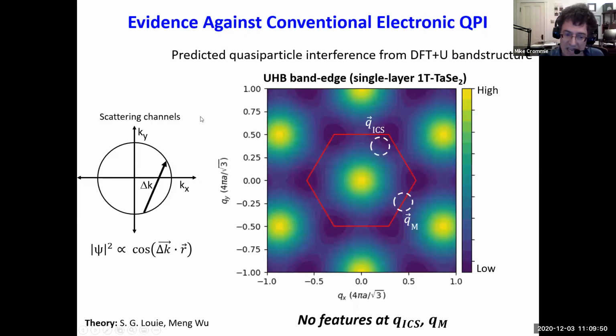And so our theory collaborators calculated the QPI pattern that you would expect for 1T TaSe2 using the DFT plus U band structure. And so here you can see that if you go, for example, near the Hubbard band edge, then you really don't have any features that would lead to periodicities at these QICs and QM. There's really no features there. There's no features in the electronic structure, at least no obvious features that would lead to that QPI. And so we think that that's evidence that QPI is not causing this.